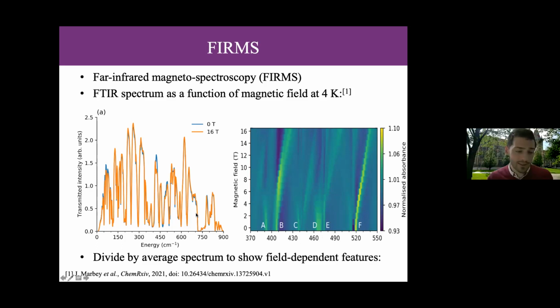Because of course, anything here that's changing as a function of field must be somehow related to an electronic state, because vibrational states should not have on their own a field dependence. So anything that has a field dependence must have some part of an electronic transition happening. So this is our attempt to measure the vibronic coupling in this material.